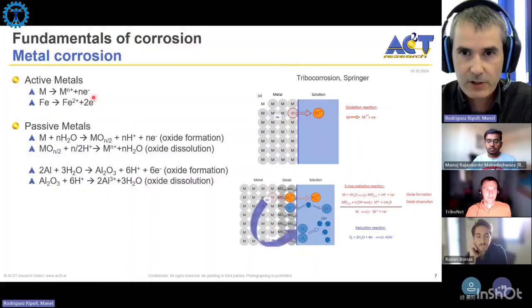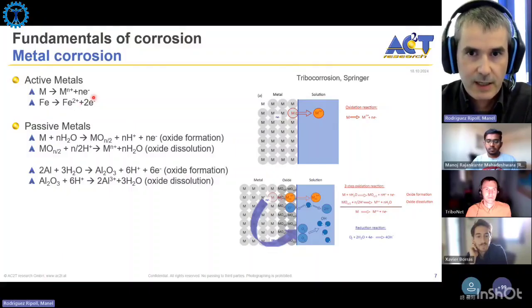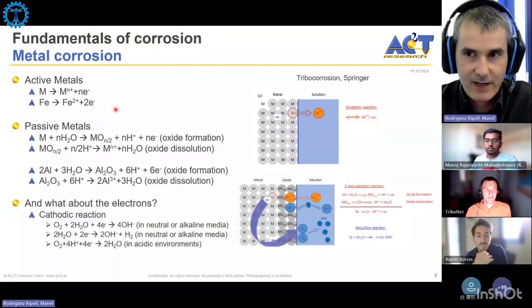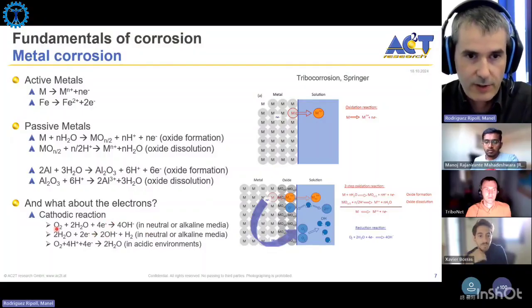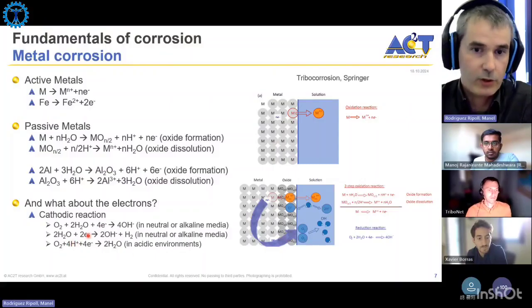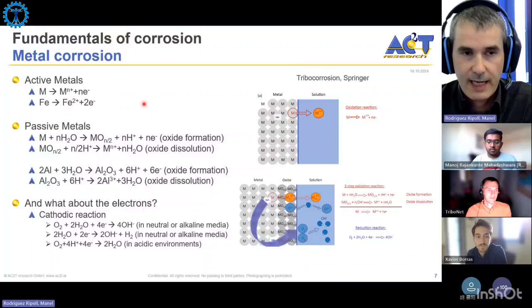And what happens with the electrons that we generate here in these anodic reactions? Well, we need to have a cathodic reaction as well, where these electrons get consumed. For example, if we are in neutral or alkaline media, we have the oxygen and water reduction equation, where these electrons get consumed, or if you are in acidic environments, the electrons can combine with protons available from the acids to form water. So basically, you emit electrons in the anodic reaction, and in the cathodic reaction, you consume these electrons. These reactions occur simultaneously.